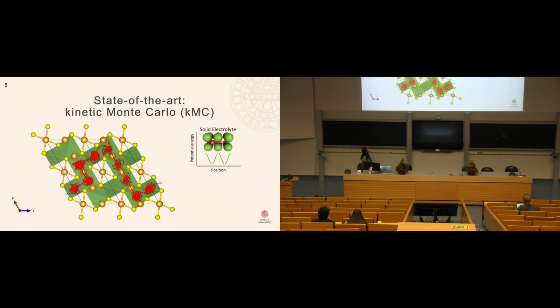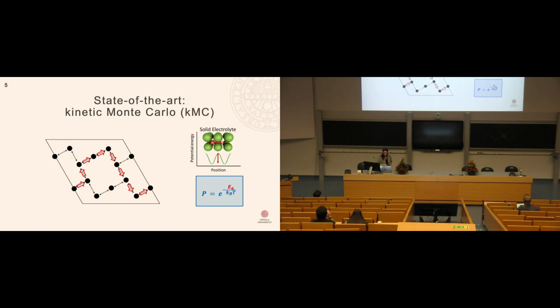So this approach allows us to extend from the constant time step molecular dynamics approach, where the sampling has spent most of its time just moving within the energy minima, to instead a lattice-based model, which only explicitly samples the transition from one energy minima to another in just one single simulation step, independent of the time that the actual process is expected to take. So the ion transport through the lattice is propagated randomly according to the probability of each process to occur relative to all other possible processes in your system.